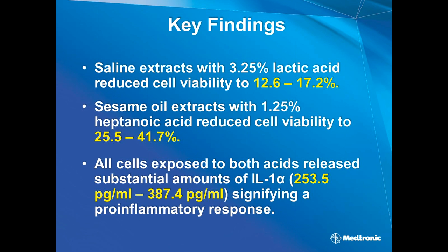That these saline extracts that were spiked with 3.25% lactic acid significantly reduced cell viability. So we definitely had over 50% kill rate. Therefore, those solutions, those extracts, or simulated medical device extracts were definitely skin irritants. Same story with heptanoic acid, even though it wasn't quite as dramatic, but cell viability was less than 50%. So again, these extracts were considered to be skin irritants.